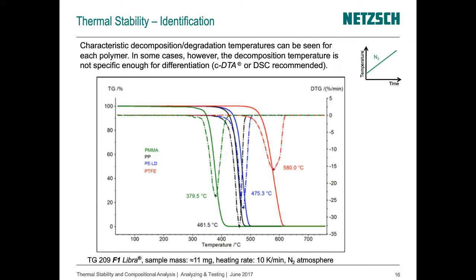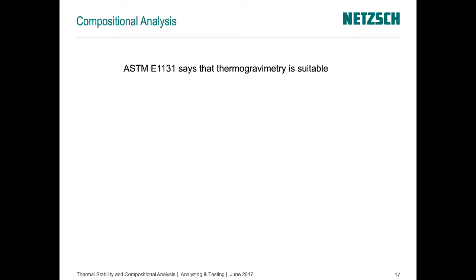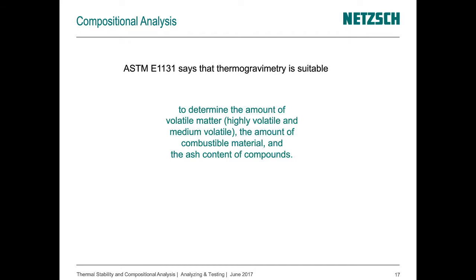Let's go over to compositional analysis, and let's have again a look inside of a standard, and this time again ASTM E1131. And this standard says that thermogravimetry is suitable to determine the amount of polymer inside of a compound, but it's not limited to that. We can also determine the amount of volatile matter, for example, plasticizer, the amount of combustible material. This can be, for example, added carbon black, and ash content. And ash content is mostly the filler, what is inside of the material.